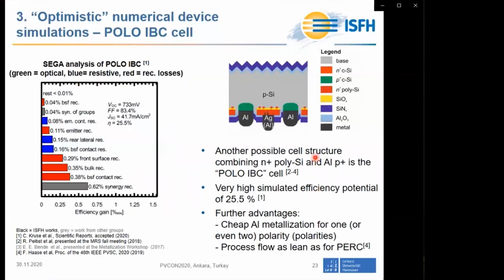Another interesting cell structure comprising this combination of electron collecting n+ poly junctions with local aluminum p+ regions for hole collection is this IBC structure shown here, which we call POLO IBC cell. For this cell structure, the simulated efficiency potential according to our numerical device simulations is 25.5%, including all relevant extrinsic losses. And this is very promising.